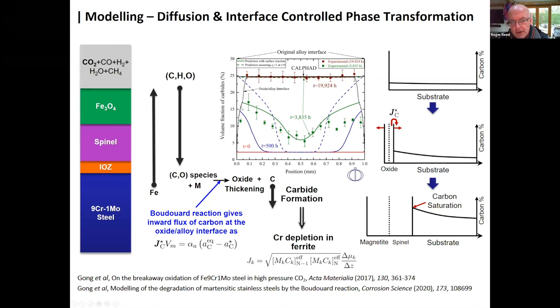So that's why this line moved in slightly. But also the boundary condition at the metal scale interface evolves with time such that enrichment increases with time. So one doesn't have a constant concentration or a constant activity. One has an increasing one with time. And so this is consistent with what's known as the Boudouard reaction, and gives a proportionality of the flux crossing that interface and the activity difference across the interface as one approaches the equilibrium.